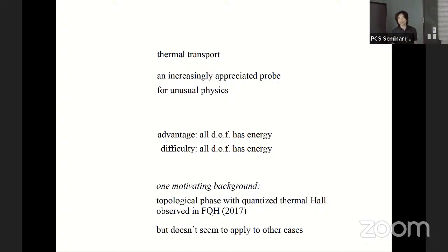One motivating background for why thermal transport has been heated in recent years is that the topological phase with a quantized thermal Hall effect has been observed, particularly in fractional quantum Hall systems. It's a very difficult experiment because it's a purely 2D system, so the heat current involved is very small and has to be measured very accurately.